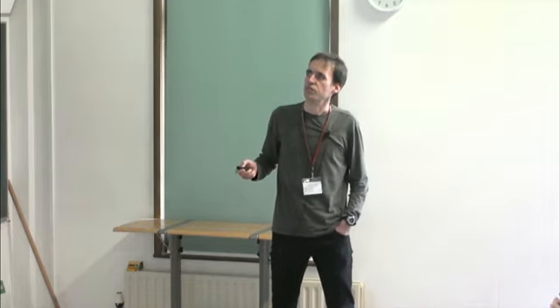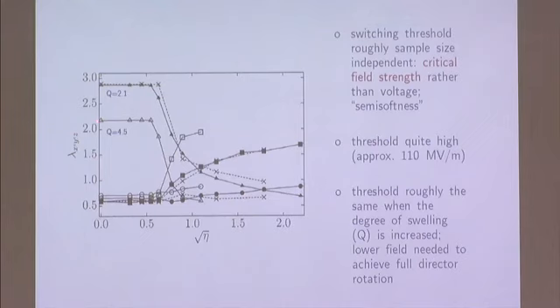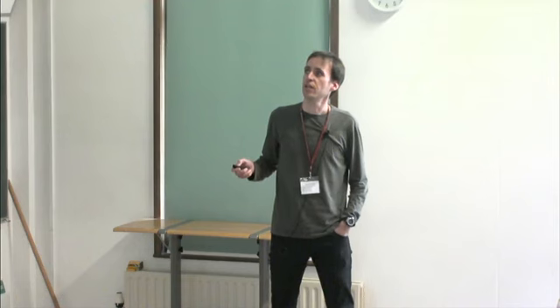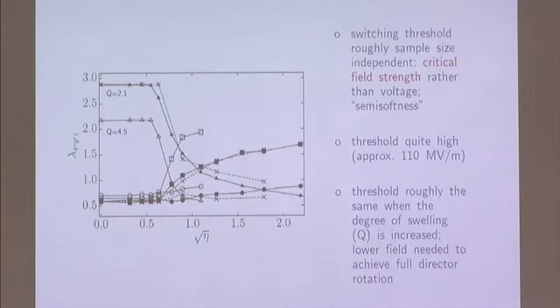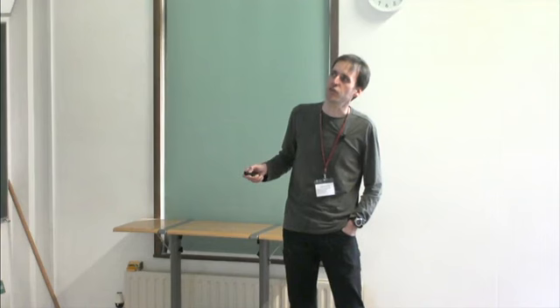The other curve here corresponds to another system which contains many more swelling monomers. And again, it turns out that many more means, okay, here the ratio is 1:1, here the ratio is roughly 4:1. So we have 4 times as many non-bonded monomers as the ones belonging to the network, and the threshold still seems to remain the same, but the overall rotation occurs over a narrower field strength range, and so such a system seems to be much more mobile.